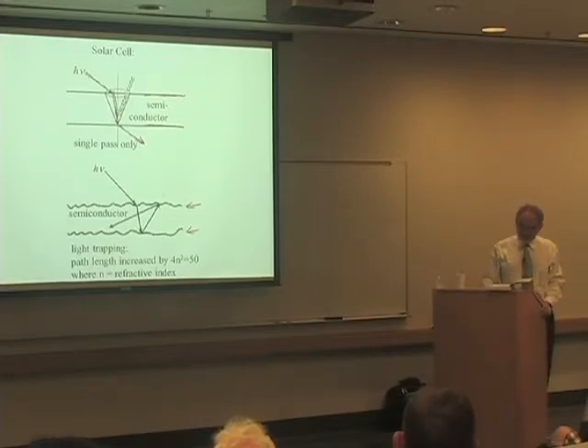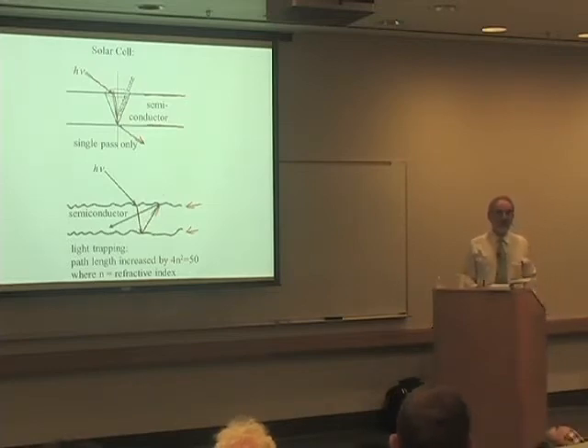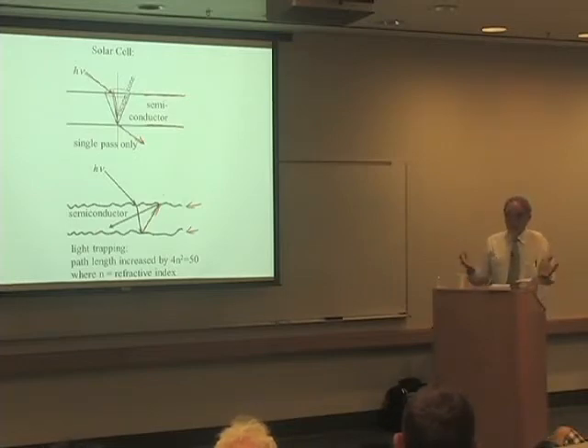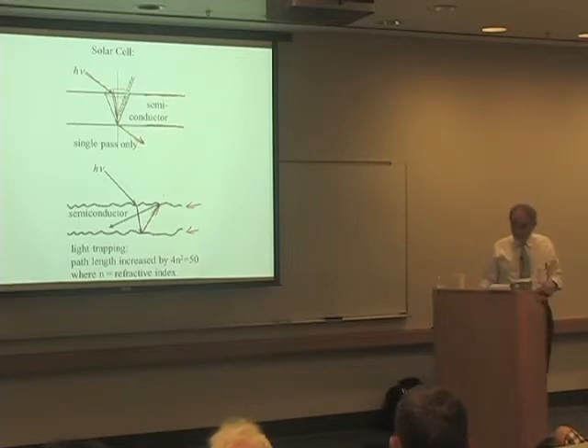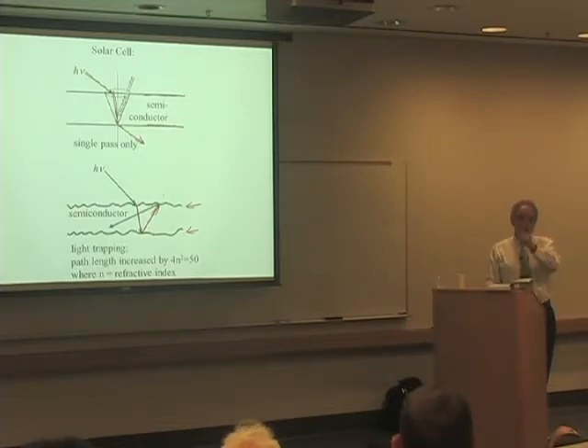The light refracts in, it bounces at some weird angle, and now it's not so easy to escape because the escape cone in a semiconductor is extremely narrow owing to the high refractive index. I think people are accustomed to a refractive index of 1.5. That's the refractive index of glass. Well, a typical semiconductor has a refractive index of 3.5. And so the escape cone is only about 14 degrees. And if you think about that, oh my god, I have to hit exactly within 14 degrees to escape. And so it doesn't escape.